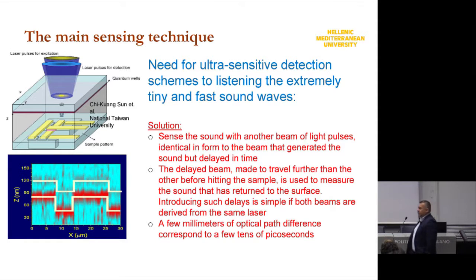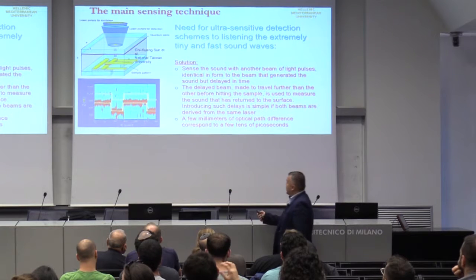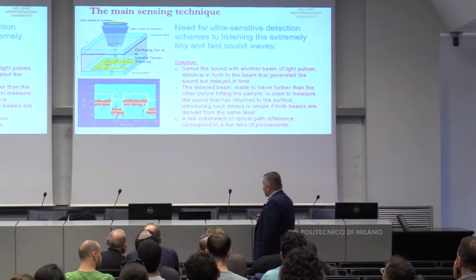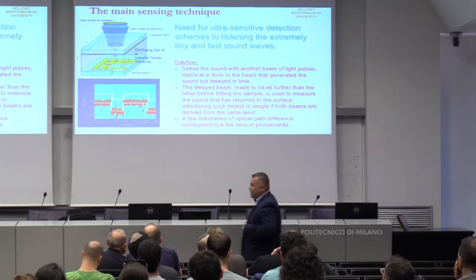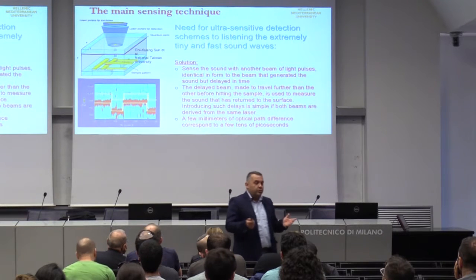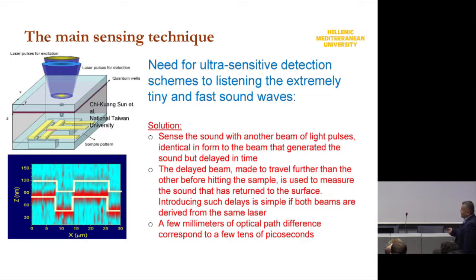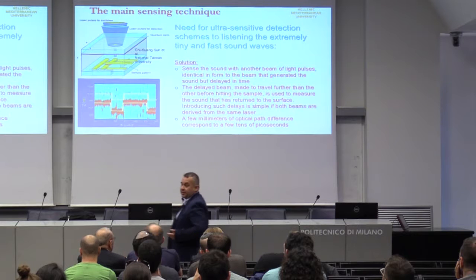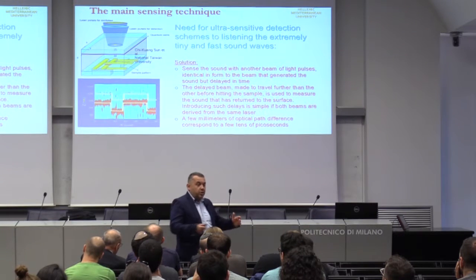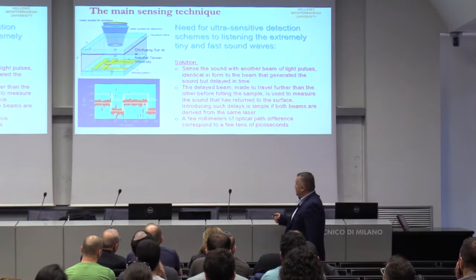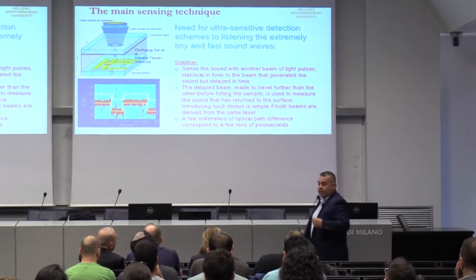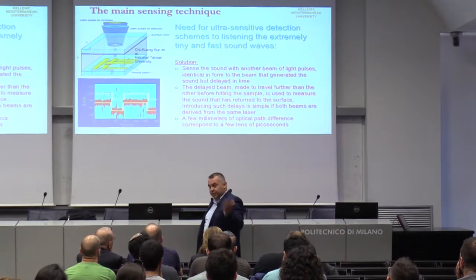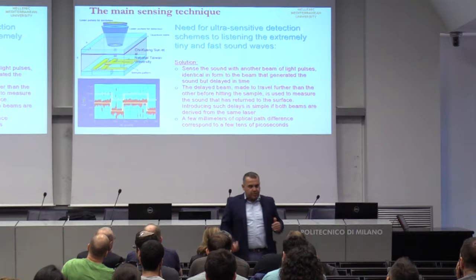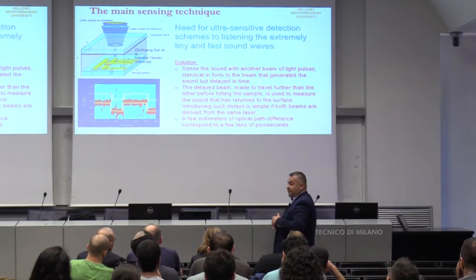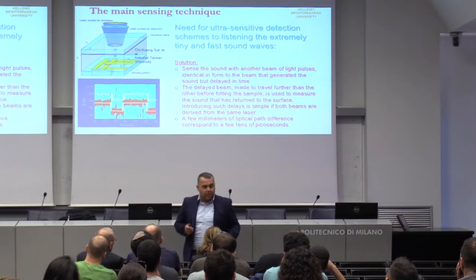Now, for example, let's see one typical experiment. We need a laser, for example, to excite the nanostrains, a femtosecond laser that illuminates the opaque material. There is the generation of these nanostrains that travel inside the material, and wherever there is a pattern or difference in acoustical impedance of the material, there is an echo that comes back to the surface. Coming with a second laser pulse with femtosecond or picosecond or nanosecond delays, depending on the distance and the sound speed, we can see modulation on the surface, either in reflectivity or in deflection of the second beam. There are a lot of different techniques where we can actually record as a function of time the arrival of these echoes, and then we can do, for example, imaging.